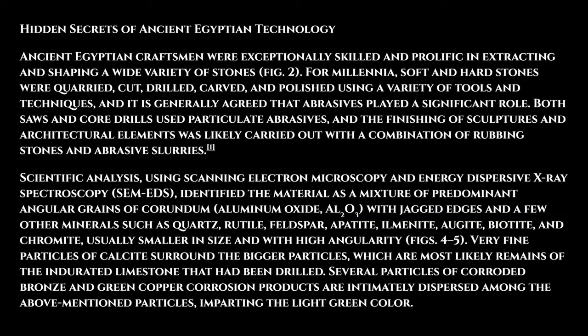Both saws and core drills used particulate abrasives, and the finishing of sculptures and architectural elements was likely carried out with a combination of rubbing stones and abrasive slurries. Scientific analysis using scanning electron microscopy and energy dispersive X-ray spectroscopy identified the material as a mixture of predominant angular grains of corundum, aluminum oxide, with jagged edges, and a few other minerals such as quartz, rutile, feldspar, apatite, ilmenite, augite, biotite, and chromite, usually smaller in size with high angularity.